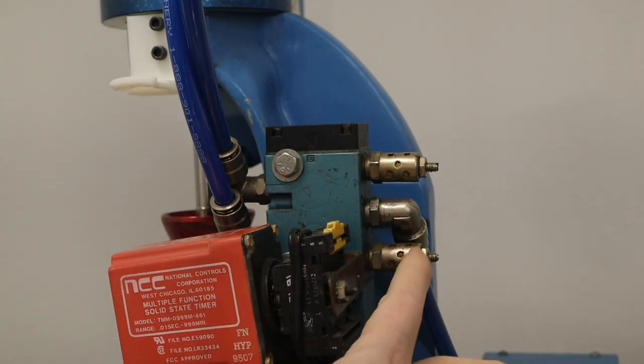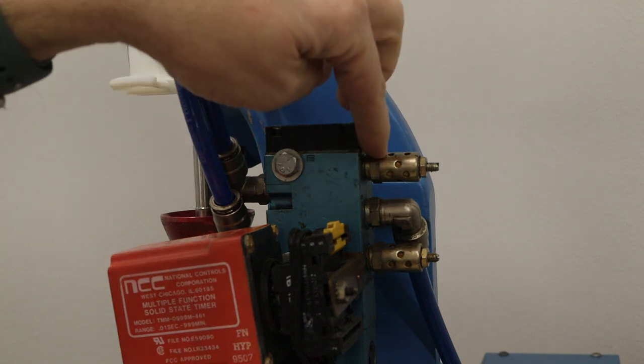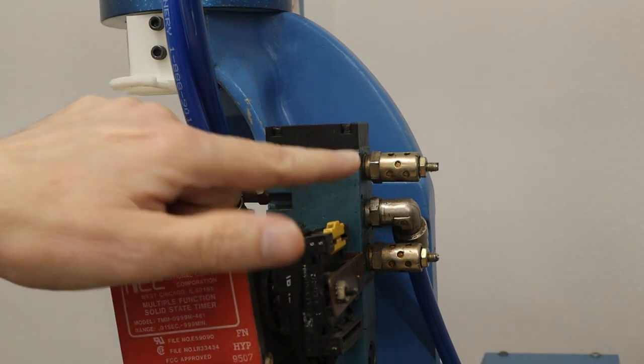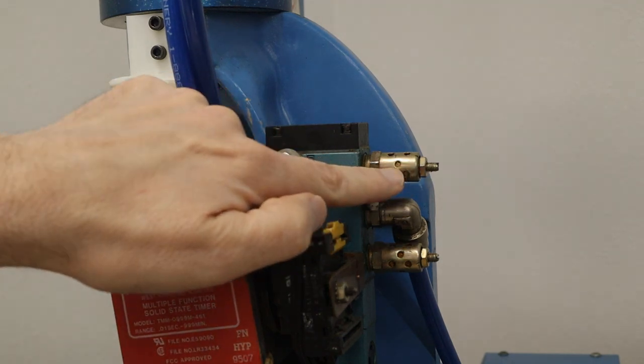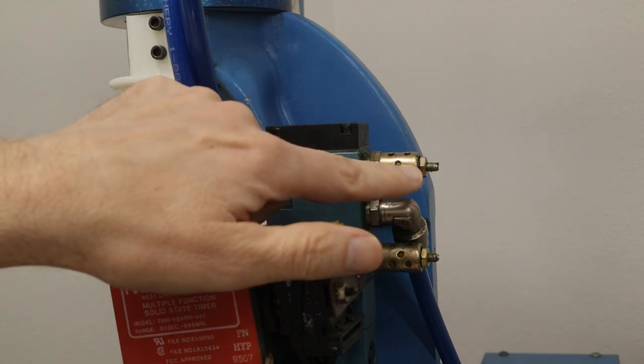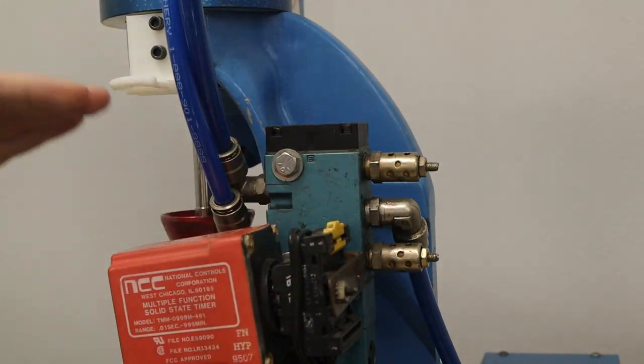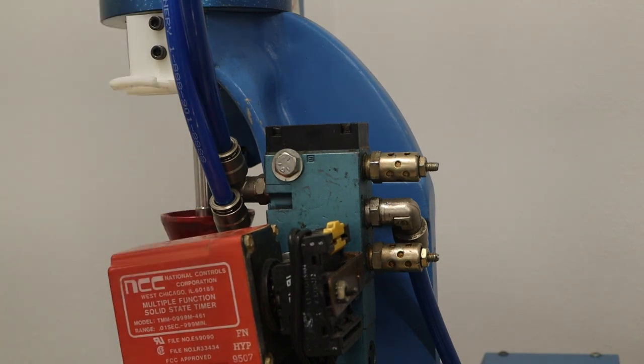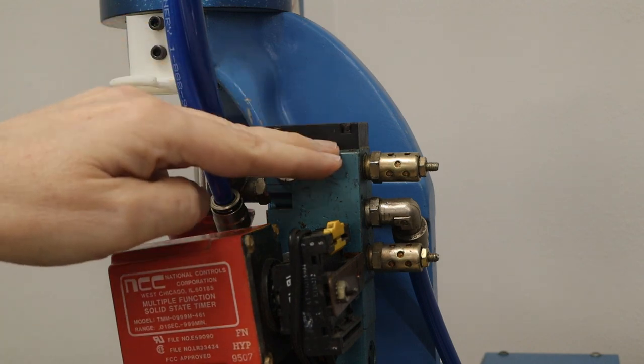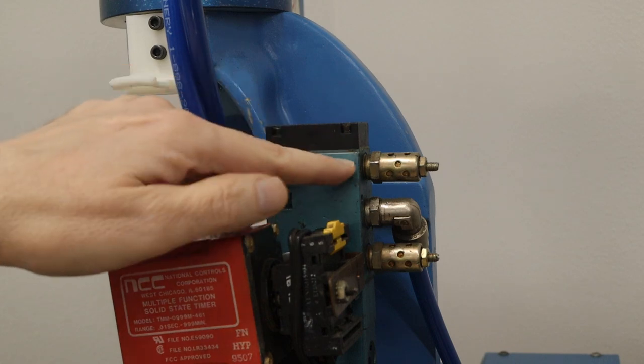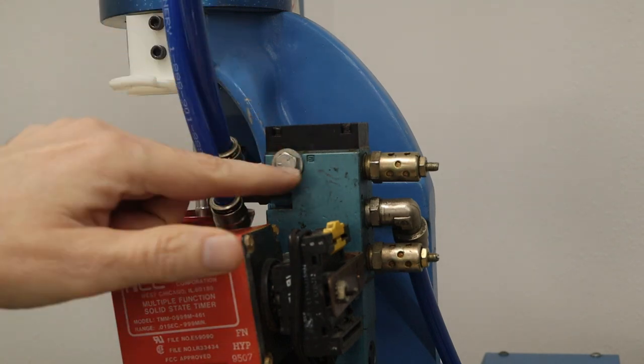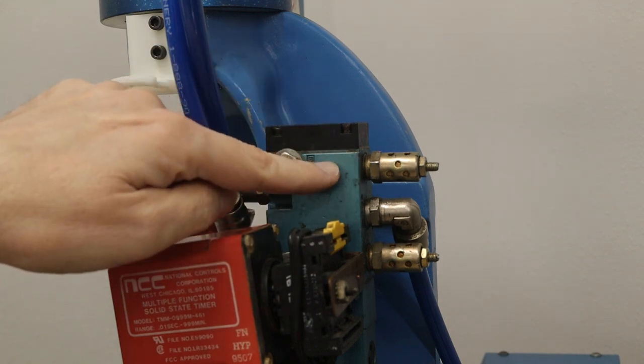These are the speed controls that are in the back of the valve. And basically what they do is they restrict the amount of air that is coming out from either of these two ports. One of the ports releases air when the piston goes in one direction. And the other port releases air when the piston goes in the other direction. So these are basically needle valves that will restrict the amount of air that can flow at a time. And so that means by changing these, you can cause the ram to move a lot slower or a lot faster. And some molds fill better if you fill it slower. Other molds fill better if you fill it faster. Generally, when you fill a mold fast, you're getting more injection pressure because you're getting a sudden spike in pressure. So that works well for small molds with fine details, but not for larger molds. Because with larger molds you might blow out the mold and get flash.